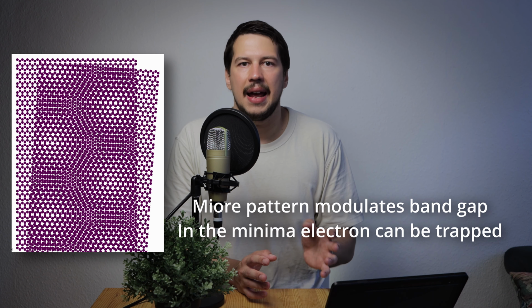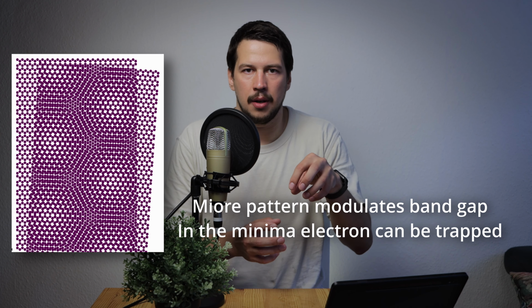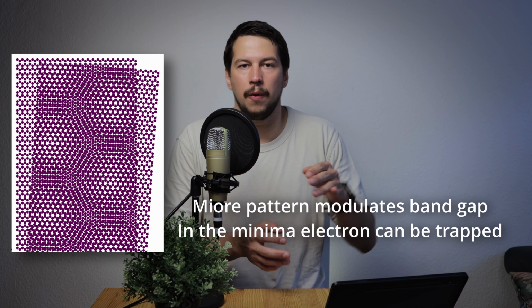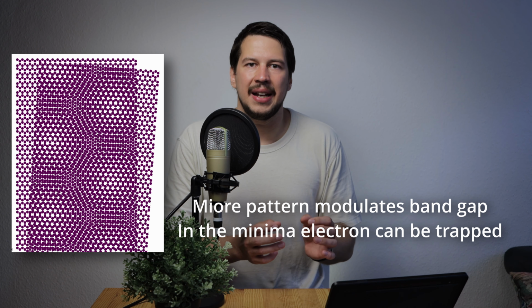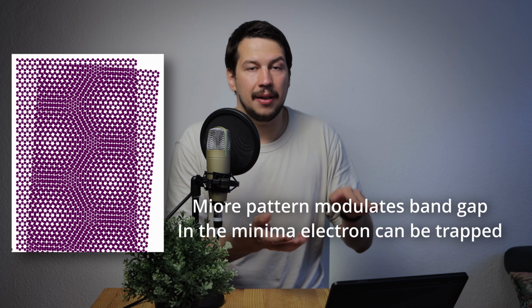Another interesting application is that you can overlay one flake by another flake, and then you have a bi- or multi-layer structure. The simplest way is to overlay the material by exactly that material, and then the interesting physics kicks in. The flake itself consists of a periodic structure, and if you overlay one periodic structure by another, and if you even tilt one a tiny bit relative to another, you will have a Moire pattern. The Moire pattern ends up with a variation of the band gap within this bilayer, and it can allow you to localize some carrier, some electron or some hole, in this variation of the potential. It is basically working as a quantum dot in the atomically thin layer.